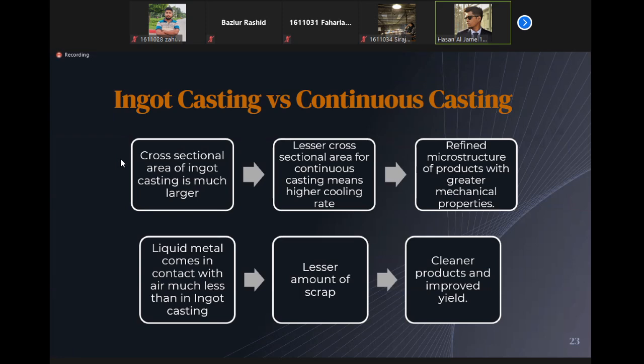I have mentioned that nowadays we are using continuous casting instead of ingot casting. So we're going to look at why it is better than ingot casting. The cross-sectional area of an ingot casting is much larger than a strand which is produced by continuous casting. And the reduced area in continuous casting decreases the likelihood of cracking due to tensile stresses that are introduced by internal thermal gradients. The reduced area also implies that the cooling rate is higher, and so there is less time for segregation to occur and more chances of obtaining a more complete solid solution. And the refined microstructure of products with better mechanical properties are found in the continuous casting process.